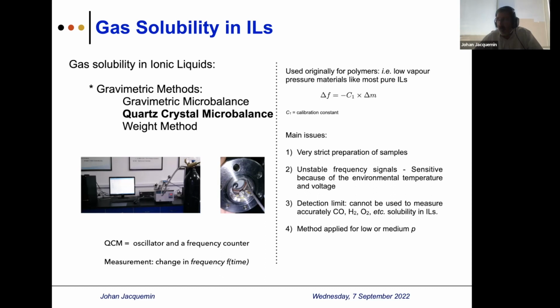Of course, this requires a very strict preparation of the sample, because this technique is very sensitive to the signal, and you may have electrical problems, which may cause artifacts in your data, I would like to say. And this must be very well controlled with the temperature of the environment and also the voltage applied. Like the gravimetric microbalance, this technique cannot be used for very low solubility and works for medium pressure.